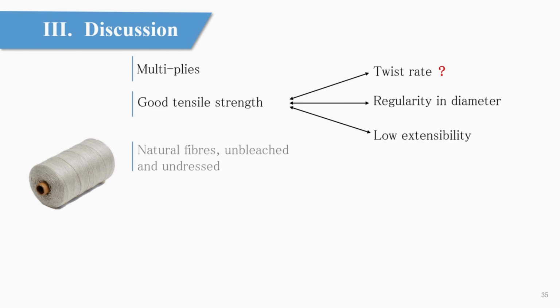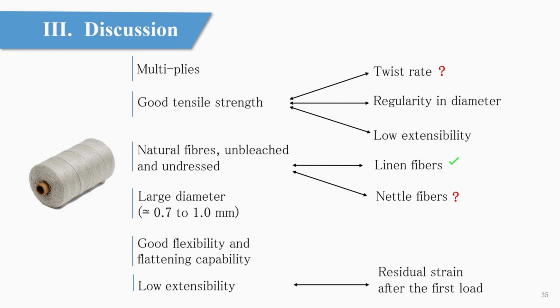Discussion on materials testing. First, about sewing thread. The number of plies is not the only factor to consider when choosing a sewing thread. Other factors also have a strong influence on mechanical strain, such as the twist rate, which unfortunately could not be evaluated in this study, and also the regularity of the diameter, which improves the stress-strain response. We saw that dressed thread appeared to be stronger, which is probably due to the fact that the addition of finish limits variation in diameter.